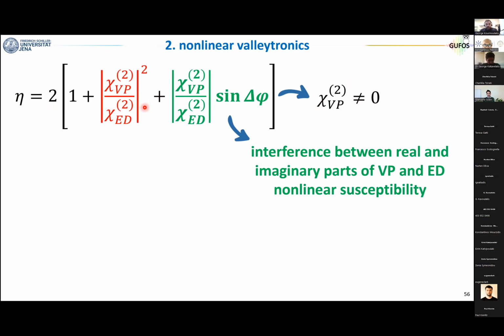And in particular, you can have an element that goes like the square of the ratio, valley to electric dipole, and something that goes linearly with the ratio plus an interference term. This interference term only arises and only comes into play if you consider that these elements are complex and you have a phase shift, so real and imaginary part, between electric dipole and valley polarization.